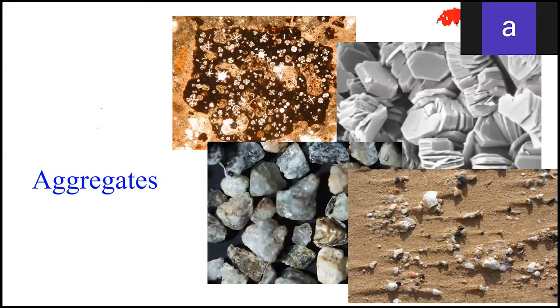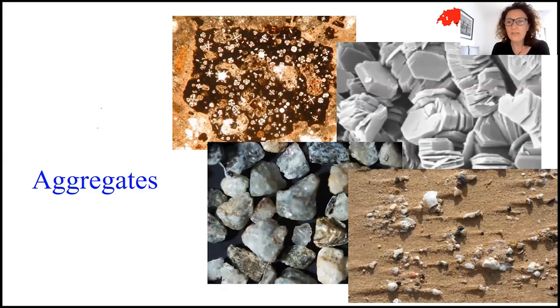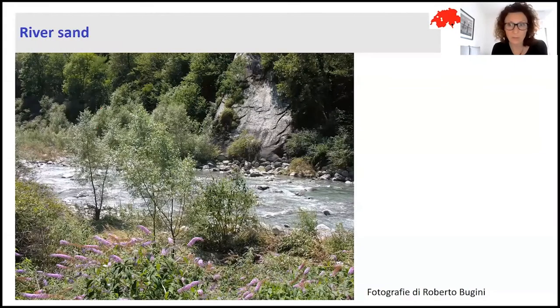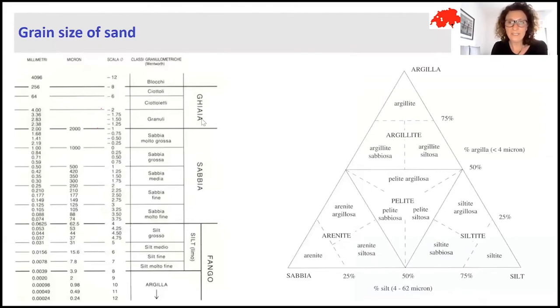Besides the binder, we can also study the aggregate in detail. The study of the aggregate is mainly made by microscopy, because it is easily observable. Normally, for the production of mortars, the aggregate is sand taken from a river. The grain size of a sand is by definition from 63 microns to 2 millimeters, and we can have fine, very fine, medium or coarse sand. Under 63 microns, we have the finer part of the sediment, mainly silt or clay materials.